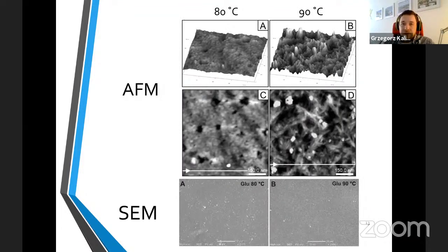And finally, microscopic images from atomic force microscopy and scanning electron microscopy present surface of samples recorded, which in 90 degrees is more rough comparing to 80 degrees, because the fibers are more densely packed and this wrapping of carbons is happening. Similar observation was made with scanning electron microscopy. We can see higher granulation in 90 degrees sample, as you can see at the bottom of the slide on the right side.